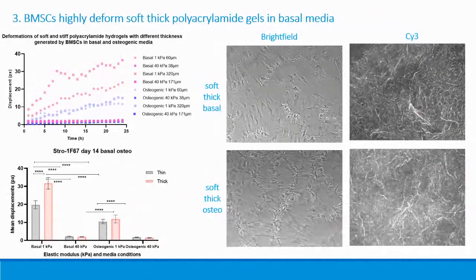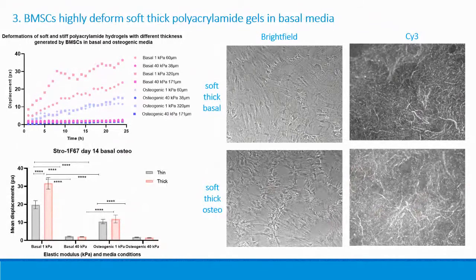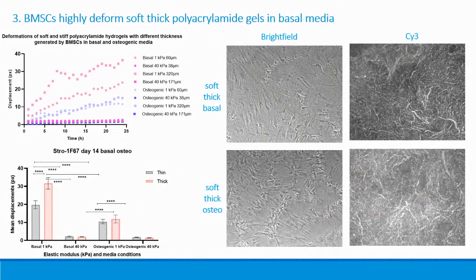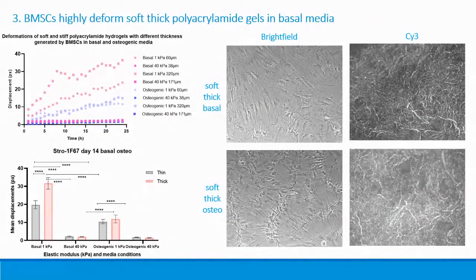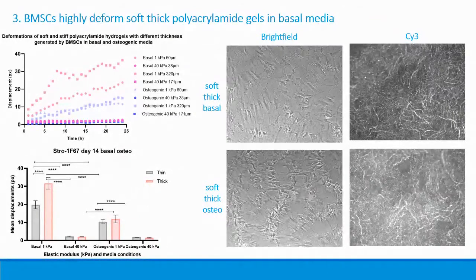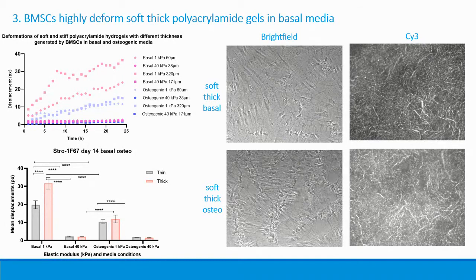We also evaluated the relation between depth sensing and osteogenic differentiation by evaluating hydrogel displacements under basal and osteogenic conditions. We found that cells still deform soft gels to a greater extent, being greater on thicker gels in comparison to soft thin gels, and the deformations were smaller under osteogenic conditions, and the stiff gels were hardly deformed regardless of the media conditions.